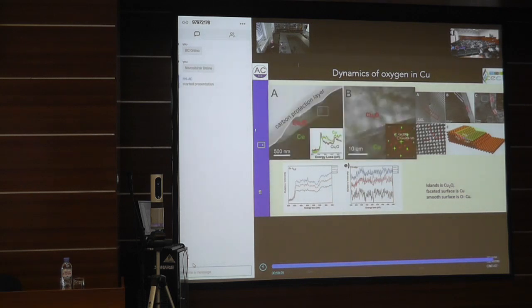We can also do energy loss spectroscopy in order to determine the ratio between copper metal and residual oxygen that is in there, that is indicated here. And here I show you one of the interfaces that we have generated, and one can do all electron crystallography, so we know exactly which part of the surface is which. So I think we have a very good understanding of what is happening when you have this dynamical situation.